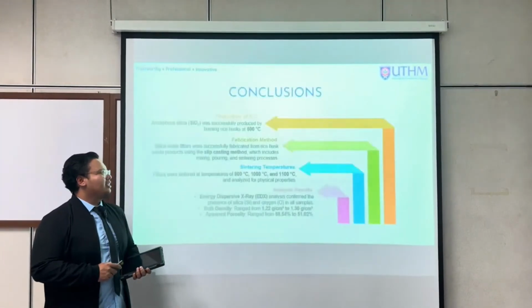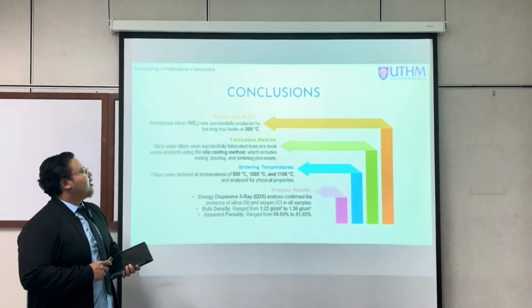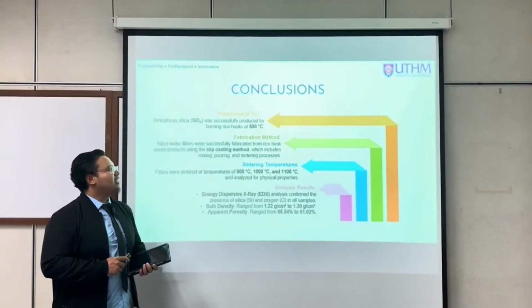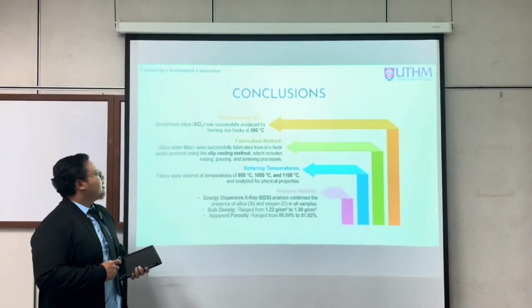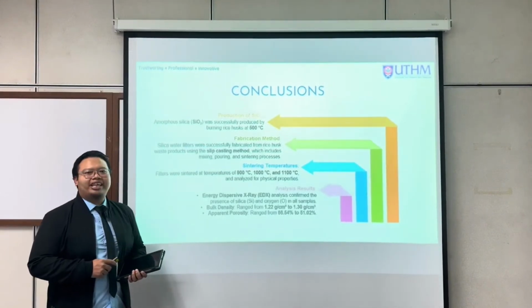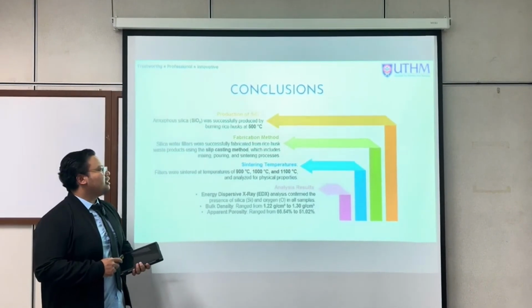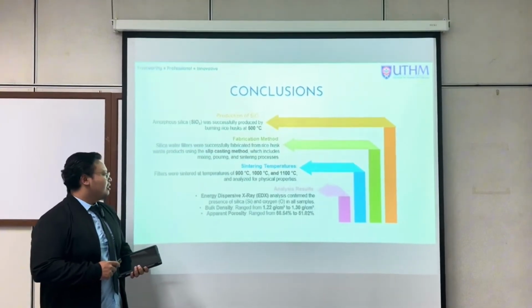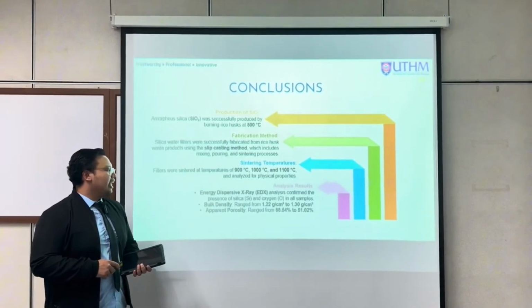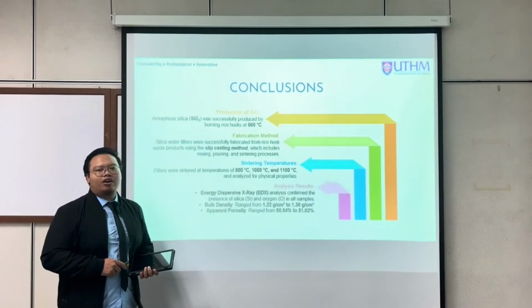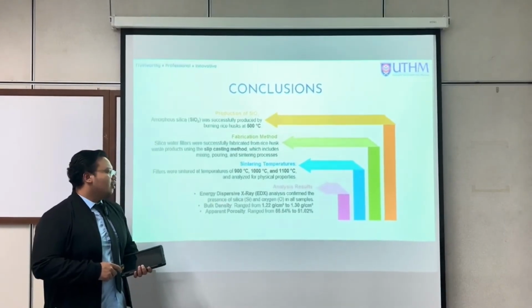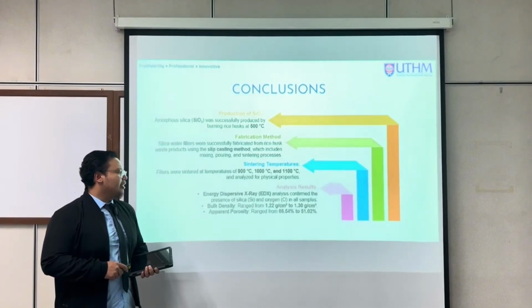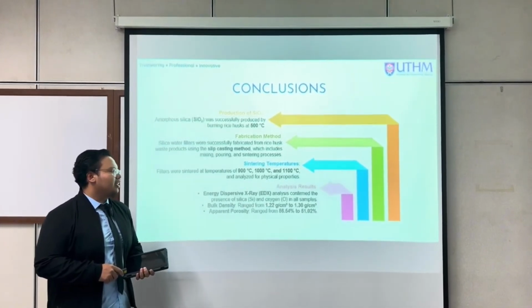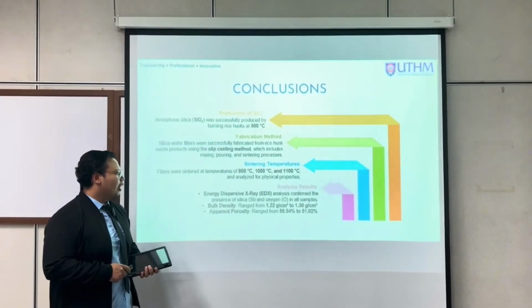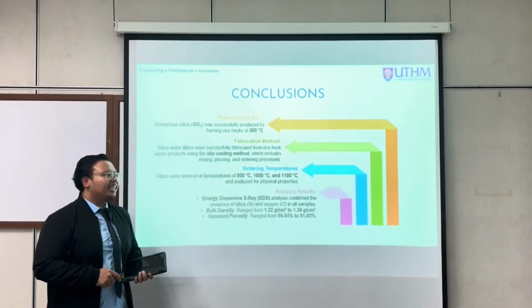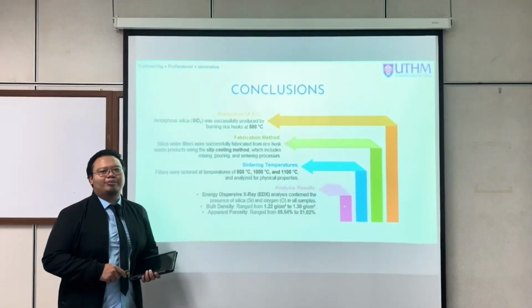For the conclusion of this research study, amorphous silica was successfully produced by burning rice husk at a temperature of 600 degrees Celsius. Secondly, the slip casting method successfully fabricated the silica water filter, which includes the mixing, pouring, and sintering process. Next, the EDX analysis confirmed the presence of silica and oxygen in all samples. For the bulk density, all samples ranged from 1.22 g/cm³ to 1.3 g/cm³. For apparent porosity, all samples ranged from 66.54% to 51.02%.